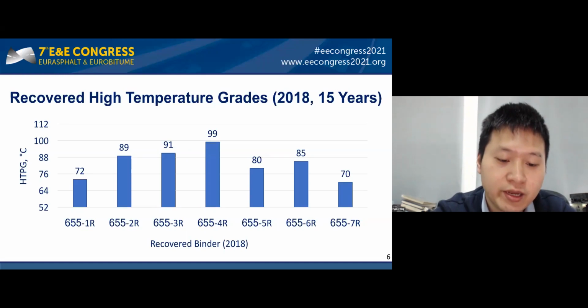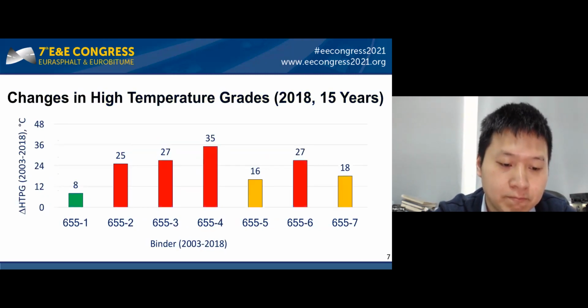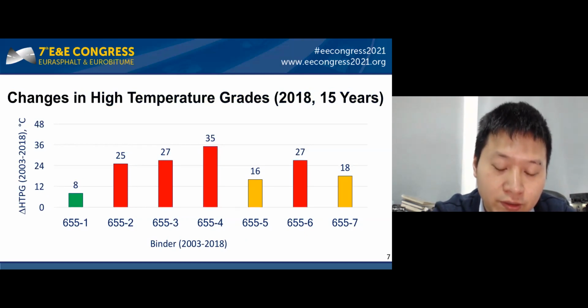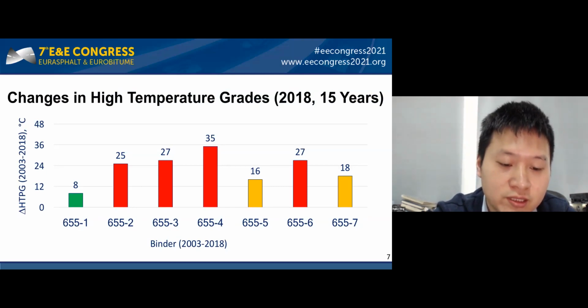The recovered high temperature grades show that some of these sections have hardened significantly. Changes from the original contract high temperature grades range from a low of 8 degrees for the stable Lloydminster binder to a very significant 35 degrees for the Ontario binder that was tainted with about 10% waste engine oil residue.